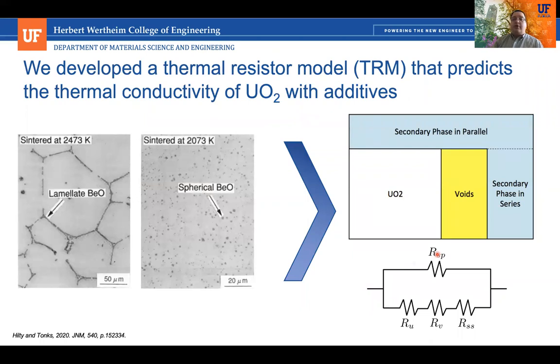The idea behind this model is we want to be able to represent the effective thermal conductivity of various microstructures with the same basic model. So we've taken this range of different structures that we could have in the fuel, and boiled them down to their most basic elements. So we have the fuel, and we have some additive that's essentially in parallel to the fuel, where the heat can transport along this continuous phase without touching the uranium dioxide. And then we have some additive that's essentially in series with the UO2, like these dispersed particles.